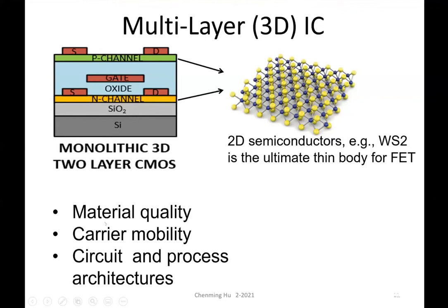So material layer quality is still to be improved. And perhaps because of that, the carrier mobility hasn't yet met the theoretical promise of being 5-10 times better than silicon at such thickness. And if we can have that kind of high mobility, we don't need multi nanosheet GAA. Just 1 sheet is enough for a transistor. So that could even make the fabrication cheaper. And the circuit and process architecture still has to be worked out. It's a lot of work that can be done.